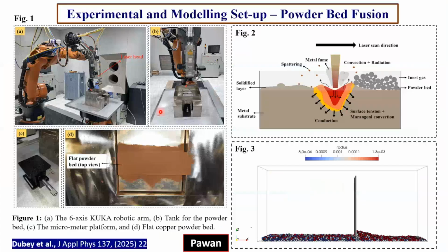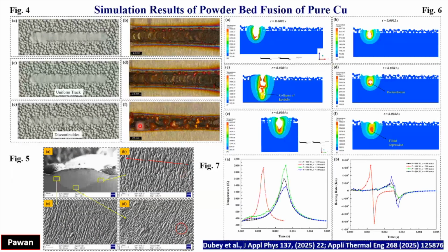The last example is coming from Pawan, who is working on modeling, this is one of the first few approaches of trying to model the thermal and compositional behavior of a powder feeding system. This is on a powder bed system, and one can produce actually on the surface and along the cross section the various temperature zones, thermal profiles, and the corresponding thermal history like cooling rate and thermal gradients and so on. He's trying to correlate this with the microstructure.